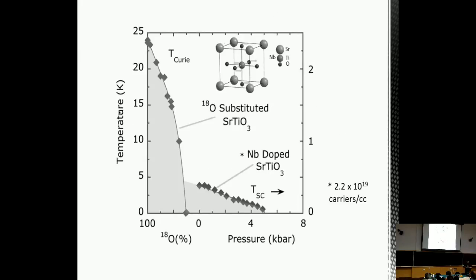So putting that together, we have a picture like this, where the ferroelectric state here is suppressed to 0 at a quantum critical point. And then as you add electrons into the lattice, there's a superconducting dome here, which forms quite close to the ferroelectric quantum phase transition. In this case, it's niobium-doped strontium titanate. So this is reminiscent of what's seen in many metallic magnets, where superconductivity forms around a magnetic quantum phase transition.